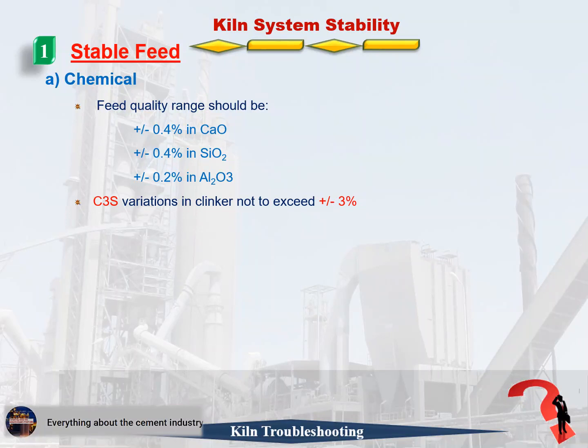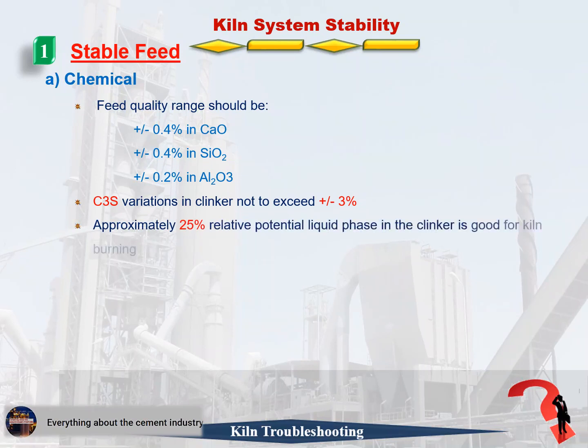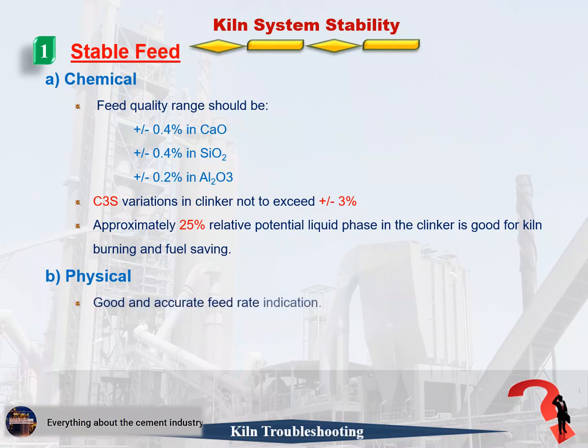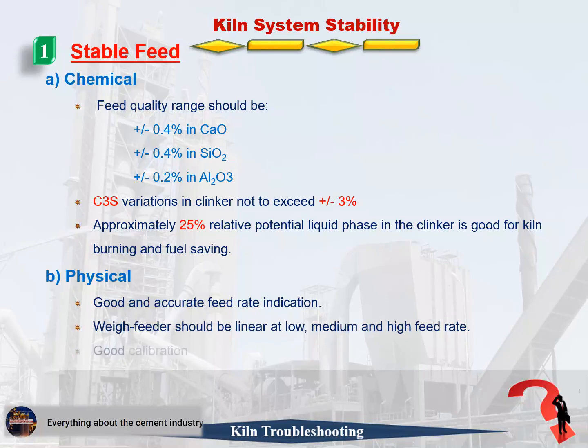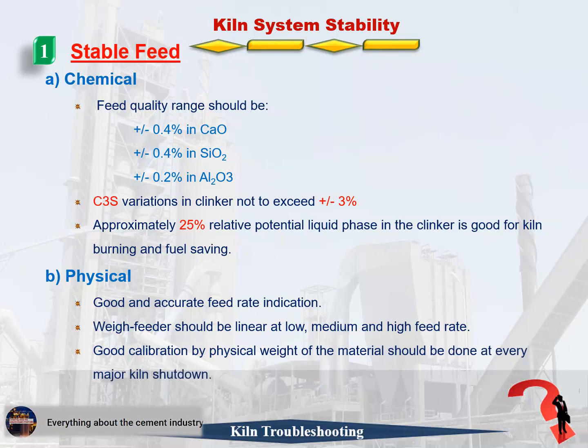Thirdly, approximately 25% relative potential liquid phase in the clinker is good for kiln burning and fuel saving. B. Physical. Firstly, good and accurate feed rate indication. Secondly, the weigh feeder should be linear at low, medium, and high feed rate. Thirdly, good calibration by physical weight of the material should be done at every major kiln shutdown. Fourthly, good feed and speed ratio.